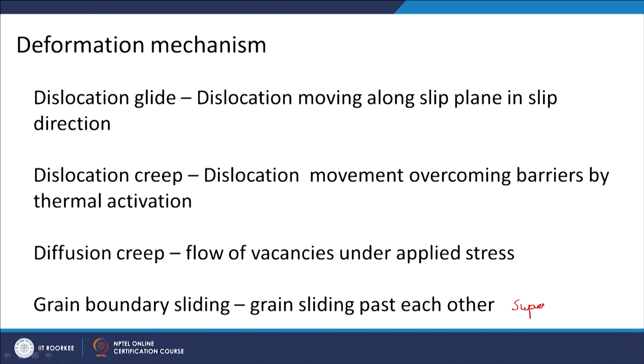At high temperature, because your grain boundary diffusion will be very high, grain boundaries are weaker compared to grain interiors. So you can have this kind of grain boundary sliding. In superplasticity, it is one of the prominent mechanisms of deformation. So you can see this in superplasticity. Diffusion creep you will usually see at lower stresses, whereas dislocation creep you will see at higher stresses. So here also there is a kind of demarcation, where you will see dislocation creep and where you will see diffusion creep.